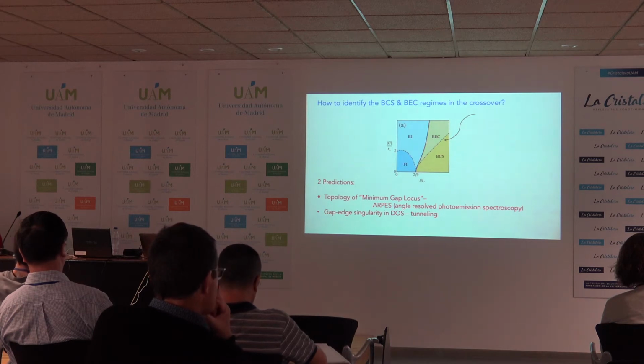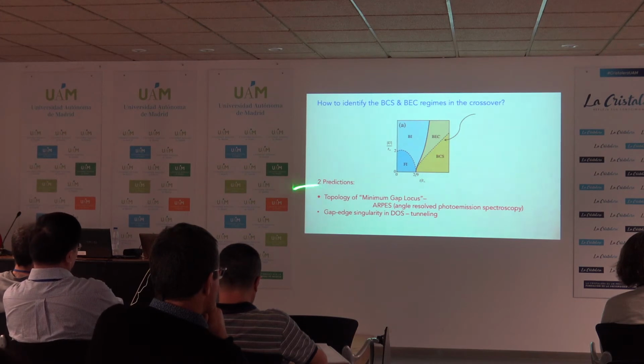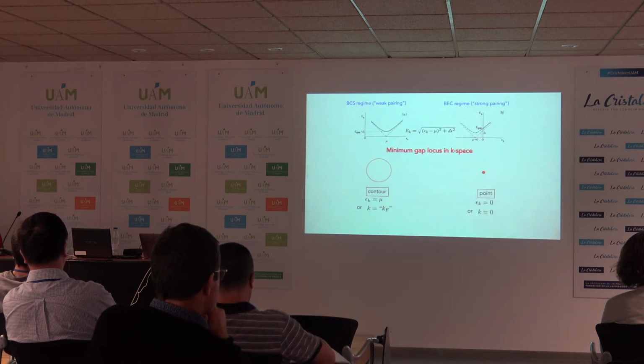The BCS-BEC crossover is really a crossover scale, so you can look at it with different quantities. If you look at it through the spectrum, we have two very definite predictions: if you look at the ARPES and look at where the ARPES has a band bending, and from that pick out the minimum gap locus, it has a very different behavior on the BCS and BEC sides. So let me just point that out here.